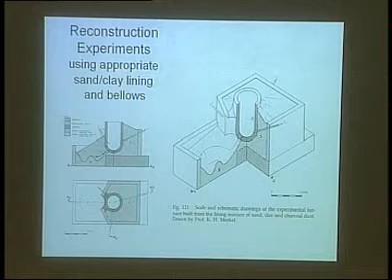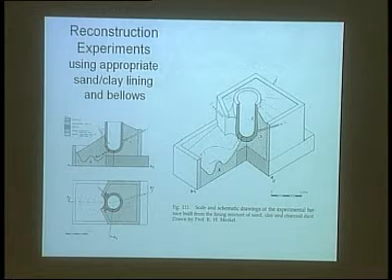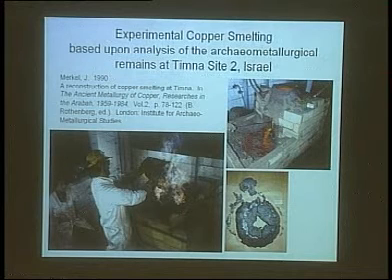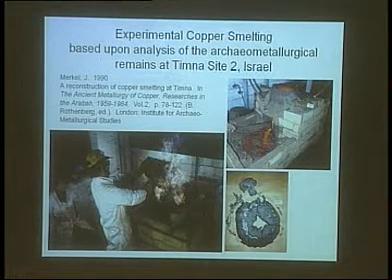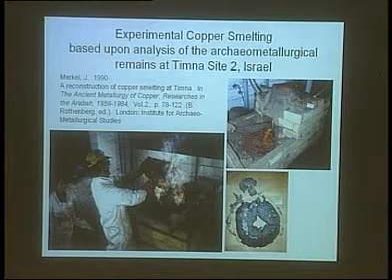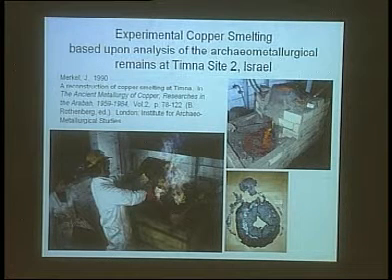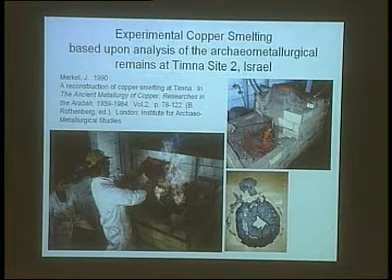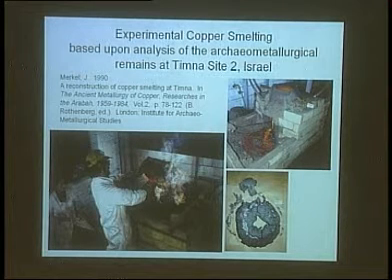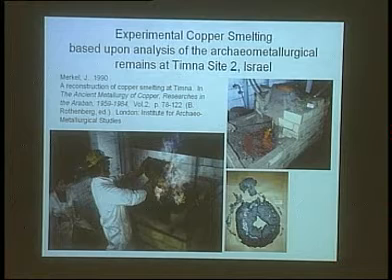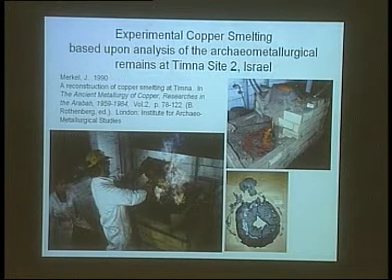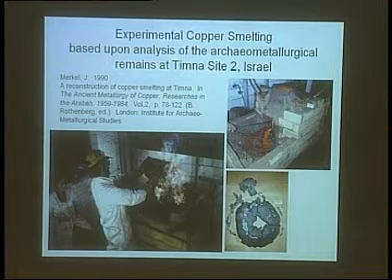The furnace walls would stand up to even higher temperatures. But there were other aspects that with the experiments, we could see how these refractories would change. And in this series of photos here, you're seeing charging ore into the furnace. This photo was done without flash, so you get an idea of the flame color on here. This is very important. Blue is good, right? That's very reducing. Too much yellow means it's too oxidizing. Okay, so we just tried to keep the flame as blue as possible here.